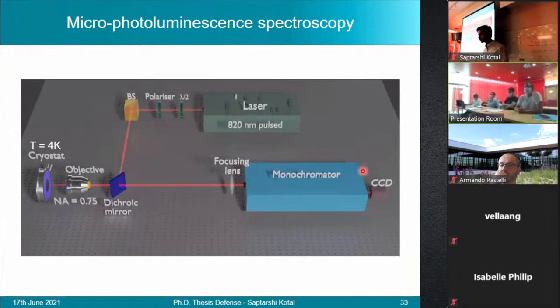And now I will present to you the characterization results that I performed. So our sample, which is kept in a cryostat, maintained at 4 Kelvin with liquid helium, is non-resonantly excited with a pulse laser tuned at 820 nanometers. The laser is focused on the sample with a microscope objective with a numerical aperture of 0.75. The objective is also used to collect the emission of the sample, which is spectrally dispersed with a monochromator and then recorded on a CCD.